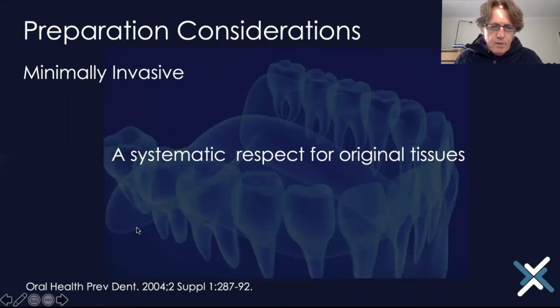So what will happen to the porcelain is it will crack. No matter whether you bond onto enamel only, the porcelain will crack because there will be stress and tension in the porcelain in the bonding process. Remember, you still have a luting cement that is going to shrink under light when you cure. So microfracture can happen, and you will not know about that until about 6 months to a year down the line. And then you have to start explaining why things are breaking.